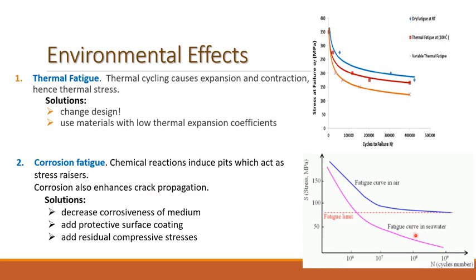If you look at this SN curve, the SN curve for material exposed in seawater has a lower fatigue life compared to the same material exposed in air. So corrosion can be avoided by decreasing the corrosiveness of the medium. We can do an electrochemical process on the surface, or we can add a protective surface coating and add residual compressive stress.